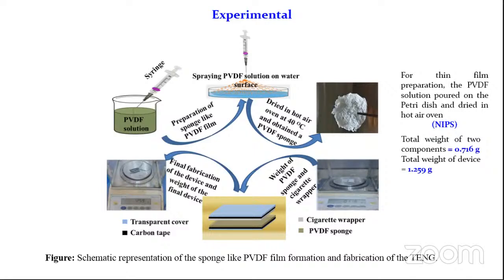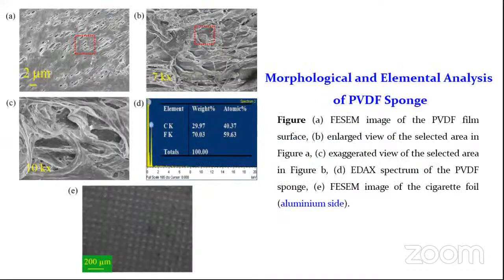After taking the polymer sponge, we have cut it in a definite size for fabricating the nanogenerator. We have seen that the total weight of the two components was around 0.716 gram, and the total weight of the device was around 1.259 gram. So it is very light in weight, but it is very susceptible to give output performance to harvest electrical energy from several kinds of biomechanical motions. So this is the morphological and elemental analysis of the PVDF sponge.